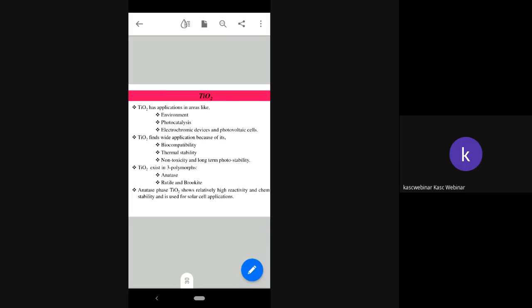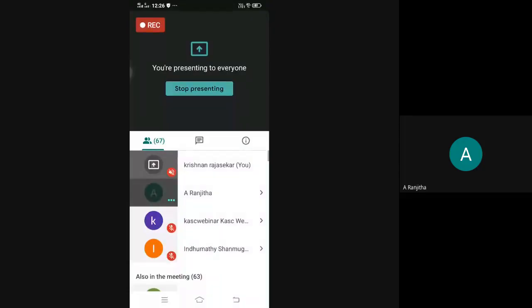And also TiO2 exists in three polymorphs, namely anatase, rutile, and brookite. Among these, anatase-phase TiO2 shows relatively high reactivity and chemical stability and is used for solar cell applications. Anatase TiO2 has a higher energy barrier than rutile TiO2. Hence, anatase phase suppresses hole transfer and back electron transfer more effectively. So, we will mostly prefer anatase phase TiO2 for preparation of photoanode material.